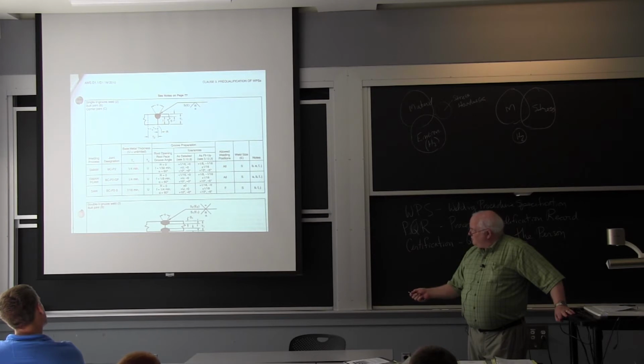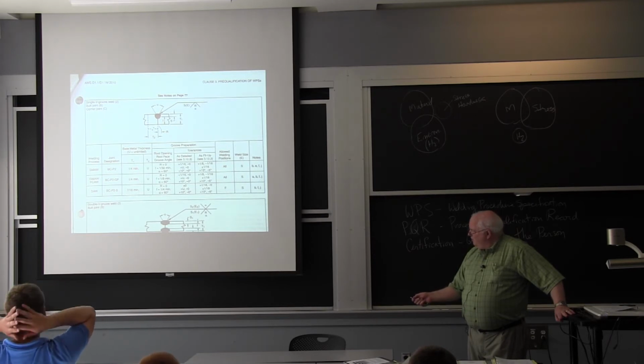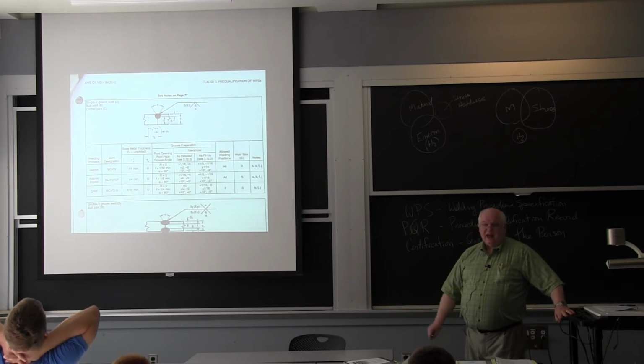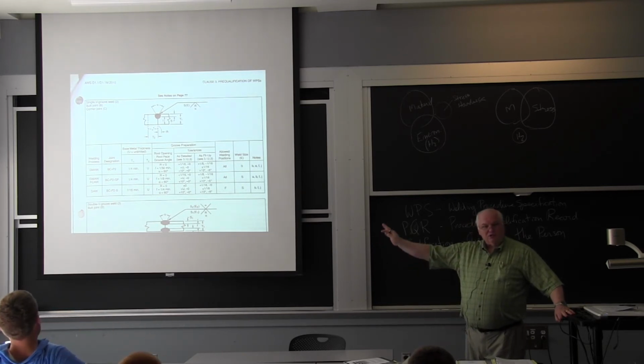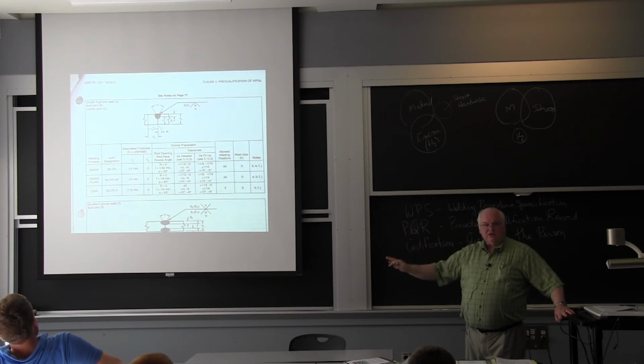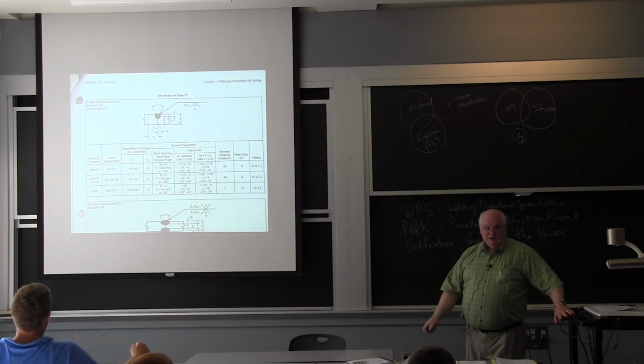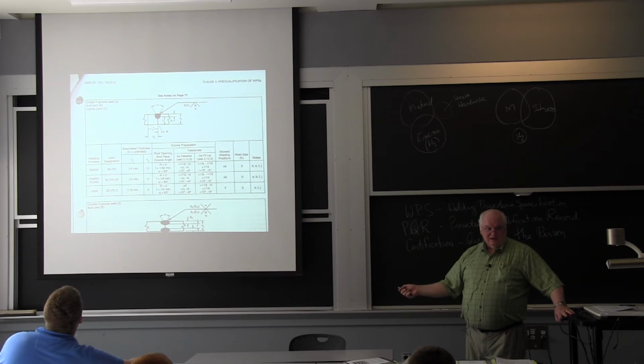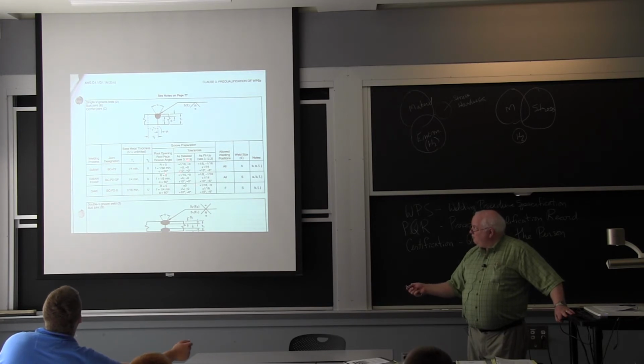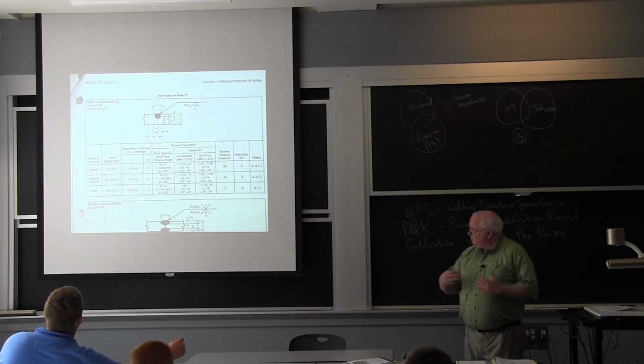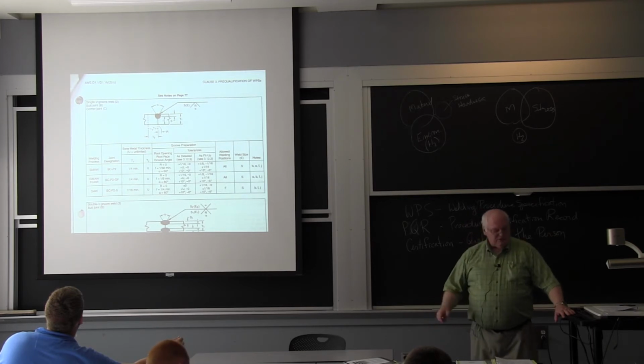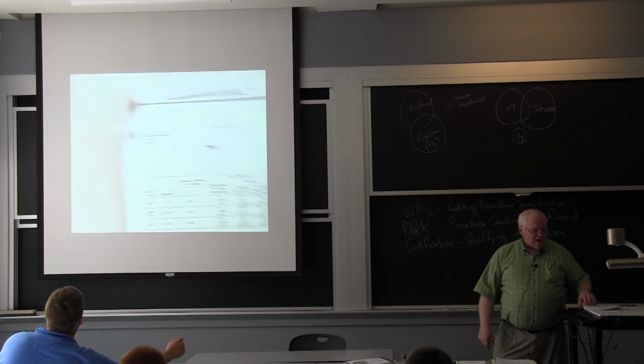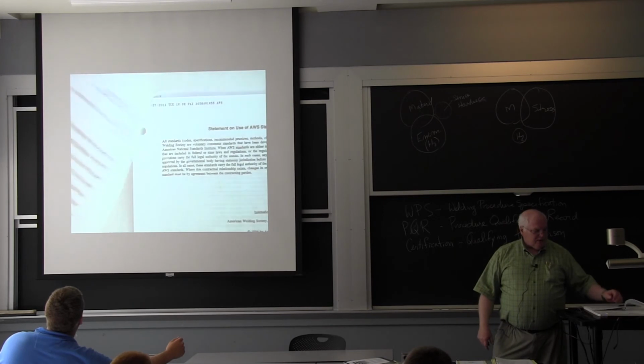The base metal thickness is 1/4 inch minimum by different processes to unlimited thickness. That can get you in trouble. Some people go to the Structural Welding Code and say, I'm going to use this for 8-inch thick steel. This is for structural welding, which is rarely over 2 inches thick, rarely over 1 inch thick, okay? And root opening, groove face, so they're telling you how closely these things have to fit together. And there's lots of other things in the code, but they can write it in a very abbreviated form.